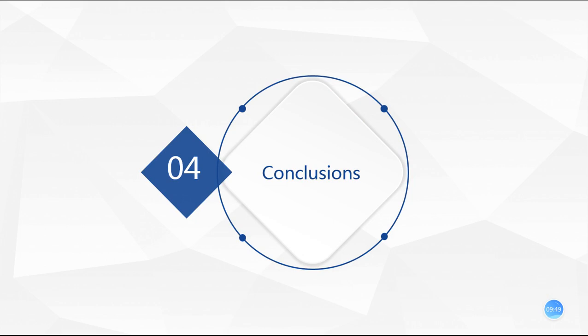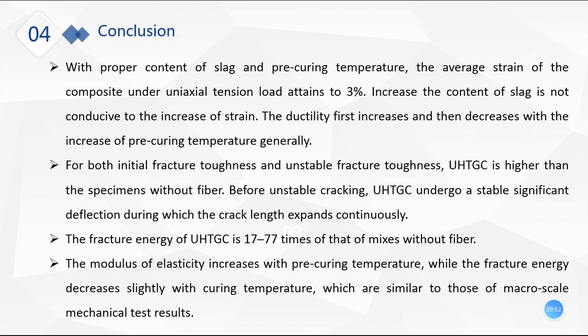Then let's come to the conclusions. With proper content of slag and pre-curing temperature, the average strain of the composite under uniaxial tension load attains 3%. Increased content of slag is not conducive to the increase of strain. The ductility first increases and then decreases with the increase of pre-curing temperature generally. For both initial fracture toughness and unstable fracture toughness, UHTGC is higher than the specimens without fiber.